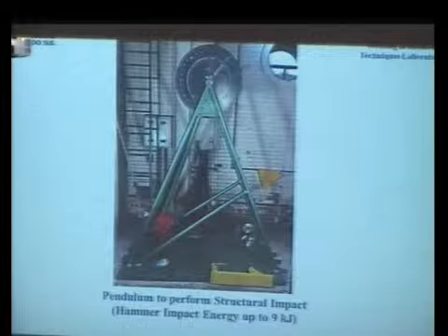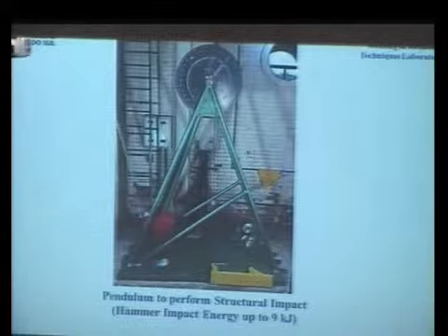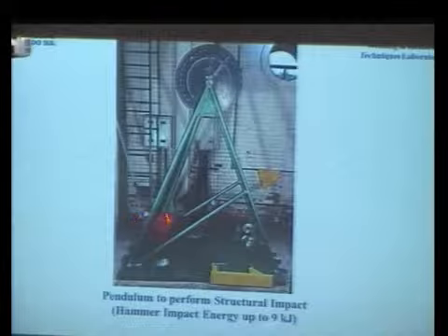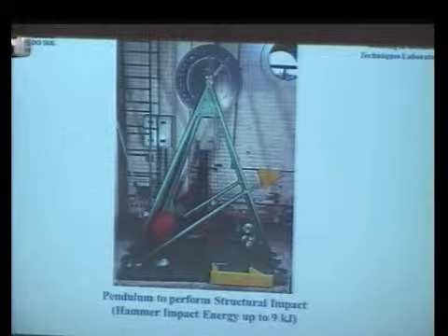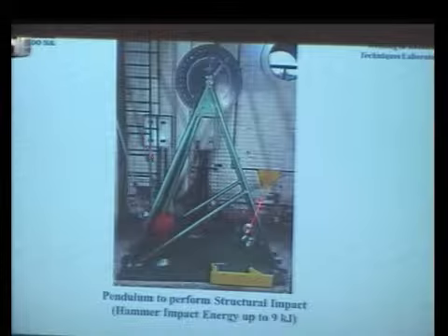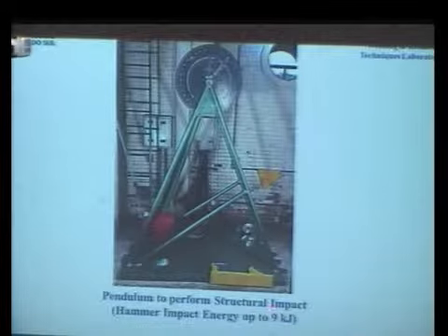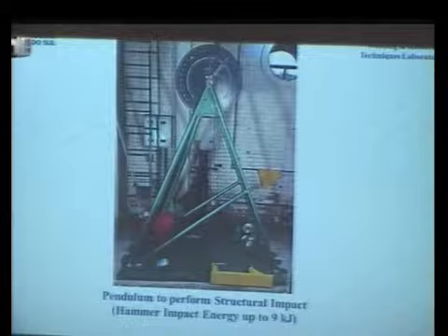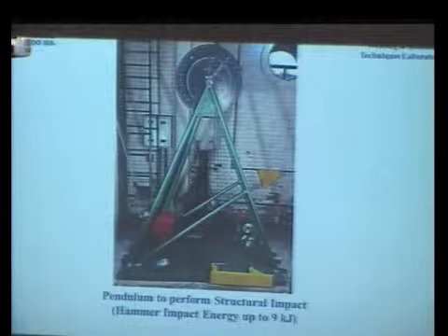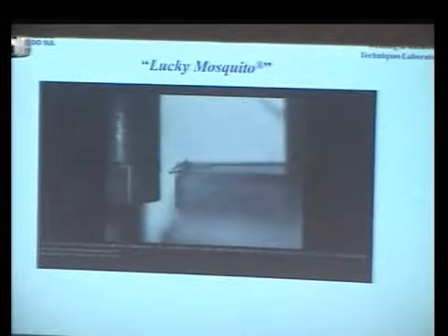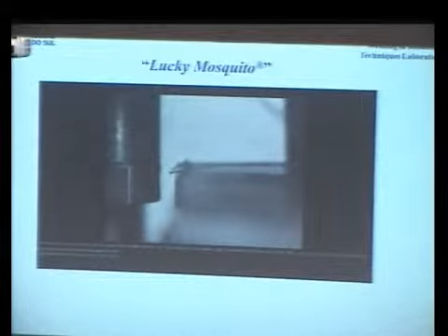And that's an impact pendulum for performing structural impact. Here it's about 207 kilos that you can raise up to 110 degrees. Yes, about that. That gives us about 9 kilojoules of energy. The impact is here. Did you understand? It's not Charpy impact. It's a structural impact. You take a welded profile and impact it. And here I show you a lucky mosquito. Here is the impact.